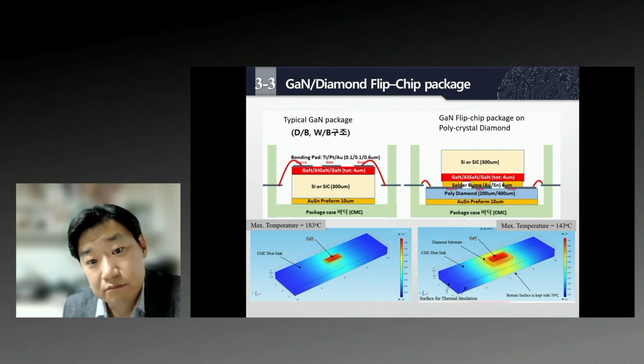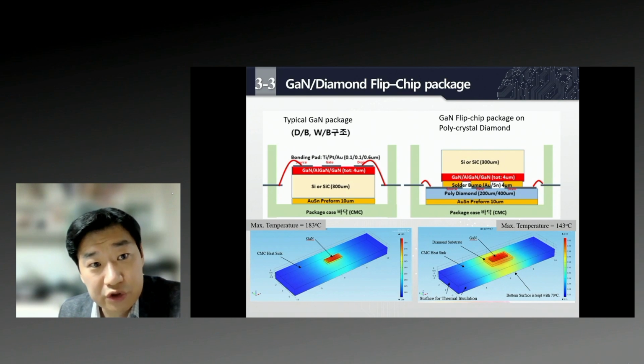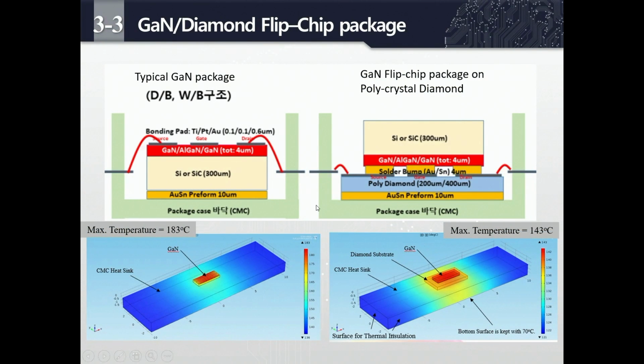So now I will talk about another method for managing the thermal issues: GaN diamond flip chip packaging. The idea is that these high temperatures occur near the surface. So if we use flip chip bonding with a very high thermal conductivity material, like polycrystalline diamond, we can reduce the high temperatures. In simple simulations, the typical GaN-on-silicon packaging shows a junction temperature of 180, but the GaN diamond flip chip shows 140, around a 40 degrees Celsius difference.